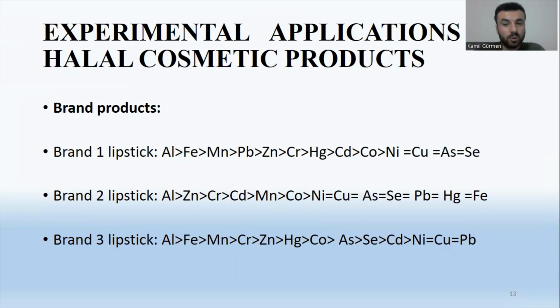The results obtained for lipstick in analysis of all brands show a high content of aluminum heavy metal. Other heavy metals that followed were iron, zinc, and manganese respectively. Brand 1 lipstick: nickel, copper, arsenic, and selenium. Brand 2 lipstick: nickel, copper, arsenic, selenium, lead, mercury, and iron. Brand 3 lipstick: nickel, copper, and lead were not found elements.